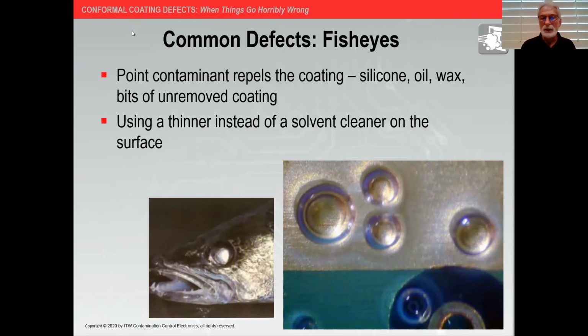What that does is as that coating goes over that little point contaminant, it raises up and it repels from that contaminant and it forms this, it's almost like a bubble, it's actually a bulge, if you will. Another source, it could be bits of scoring dust, it could be junk coming in from your ventilation system, could be a piece of lint off of your smock. Anything that can settle on that surface prior to coating can be considered as a point contaminant or a potential point contaminant.